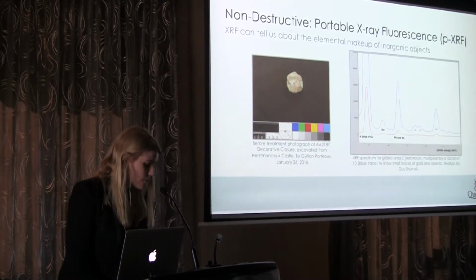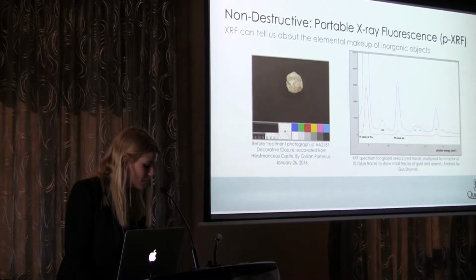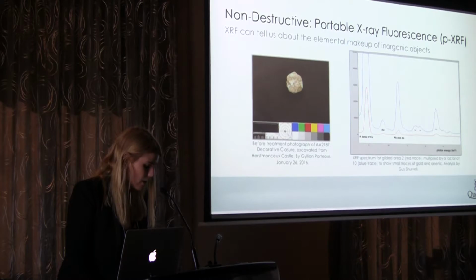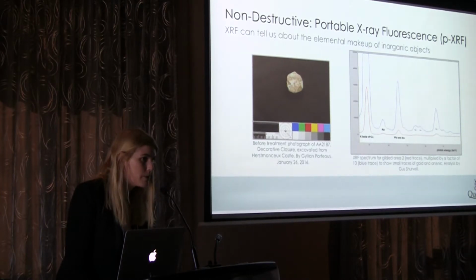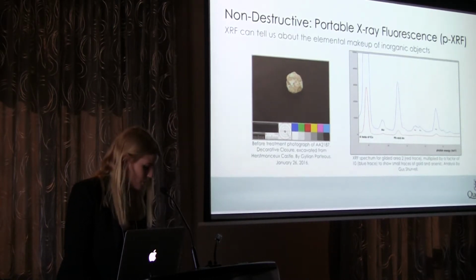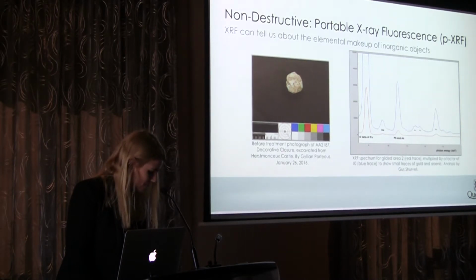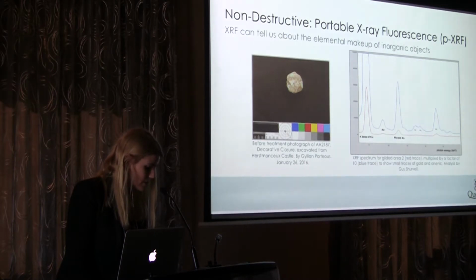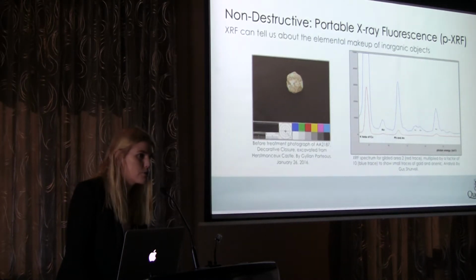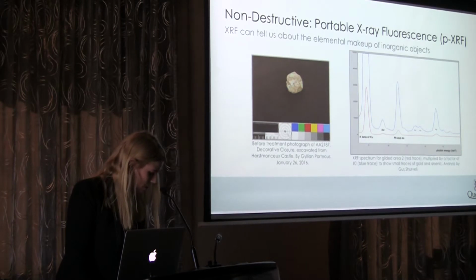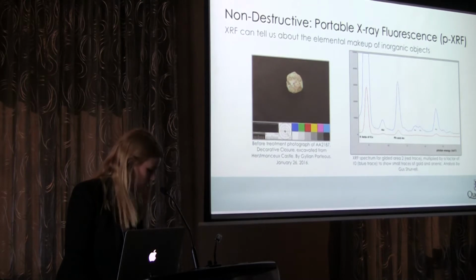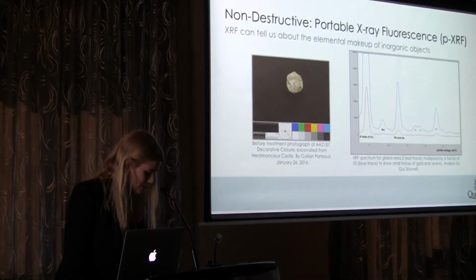XRF is a surface technique which can tell us about the elemental makeup of an inorganic object surface. We use it extensively in our work with Herstmonceux objects, as we predominantly deal with metal objects, which of course are inorganic. Our common dealings with metal excavated objects is likely because these objects seem to endure the burial environment at Herstmonceux quite well. Regardless, as you can see from the figure on the slide, the burial environment still takes its toll on the objects we receive, which can make identification difficult.